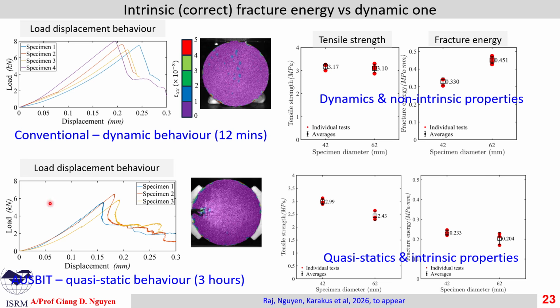So if we use our well-controlled test, the fracture process is very long. It is very gradual, and we can capture the full snapback curve from which we can reliably obtain the tensile strength. In this case, it is slightly below the indirect tensile strength obtained from the standard Brazilian disc. The fracture energy in this case is much lower than the case in which dynamic effects are not removed, which is the case of standard Brazilian disc testing.